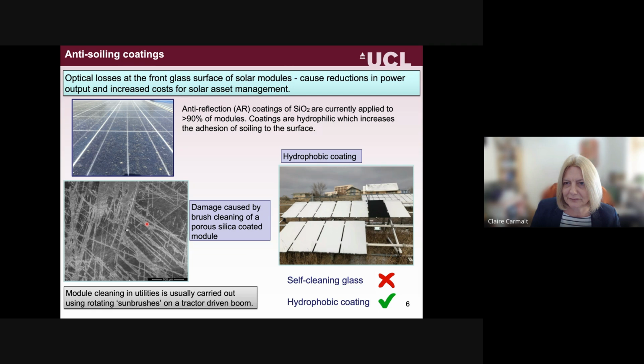So attention's been changed from hydrophilic coatings to hydrophobic. And this shows you an example of some solar modules where one panel, which is this one in black, has been coated with a hydrophobic coating. It's then snowed, and you can see that on all the other panels, snow's accumulated onto the panel, but on this one where it's hydrophobic, it's completely clear. So we're very interested in looking at developing hydrophobic coatings that could be used for anti-soiling coatings in this application, or indeed other applications as well.